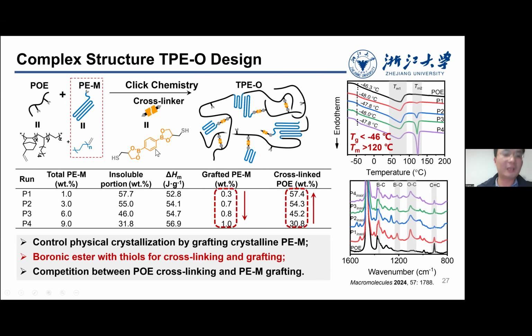And finally, we find maybe we can further simplify the process. For example, if we have some elastic backbone with some pendant groups here, for example the vinyl groups, maybe we can just use the monomers. They can be physically crystallized, and we can combine them together with a cross-linker with dynamic chemistry bond connected with the thiol group. The thiol can react with the vinyl groups here, and this dynamic chemistry bond can exchange at high temperature. So in this way, we can develop a more complex TPOE or polyolefin elastomer product. And we have a grafted structure. It can be increased from 0.3 to 1%. And the cross-linked amount can reduce from 57 to 30.